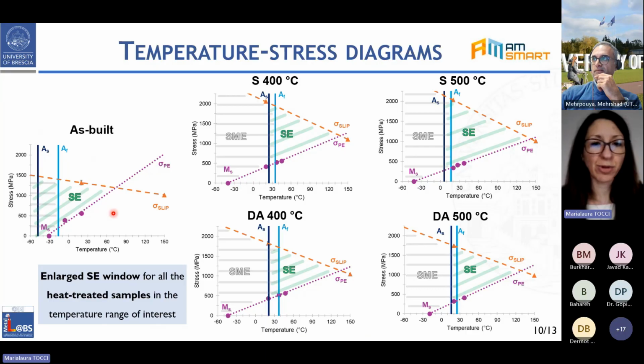and it is possible to observe that with the heat treatment, we have an increase in the critical stress for the slip deformation, and instead a decrease in the pseudoelastic stress, and an increase, as we said, of the transformation temperature. This results in an enlarged superelastic window. Again, something positive if we consider the application we have in mind. This enlargement is particularly evident for the treatment with aging carried out at 500 degrees.